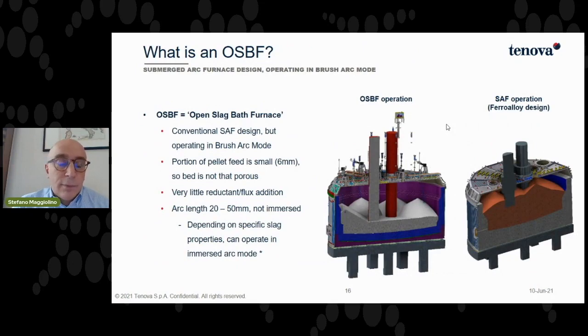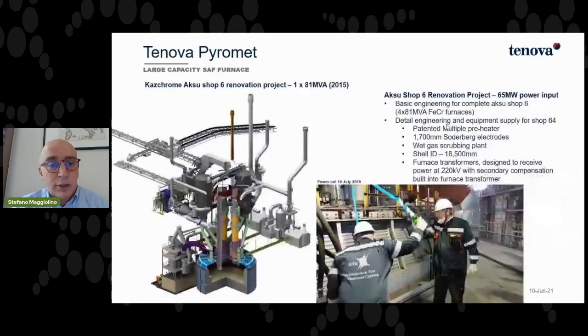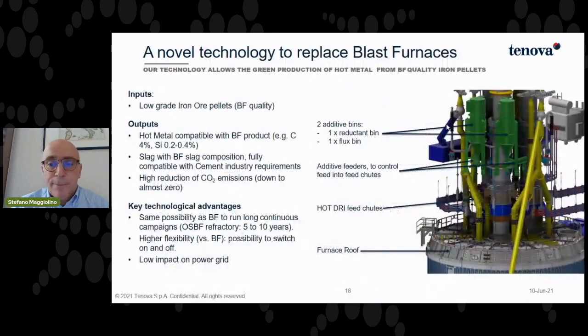The reducing furnace is basically a smelter furnace operated in a submerged arc mode. So a very standard static electric furnace operating with Soderberg electrodes. This is, for example, a reference of a similar furnace used for ferroalloys. So it's a very proven solution that works even in tougher conditions than those with the DRI. And again, the hot metal that is produced is totally compatible with the one currently produced with the blast furnace, as well as the slag.